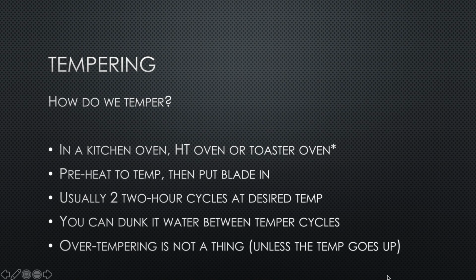And guys, you can dunk it in water between temper cycles. You don't need to let it cool to black in still air. Just go dunk it in water. It's not going to hurt it. It's not going to crack it. Don't worry about it. And there's no such thing as over tempering. If you leave your knife in the oven accidentally and fall asleep overnight, it's fine, as long as it didn't go over its temp.